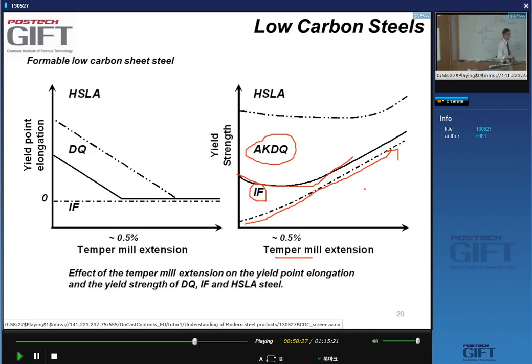So is it necessary to temper roll IF steels? Well, not to remove a yield point. But remember that in temper rolling you achieve three things: removing the yield point elongation, applying a specific roughness, and final correction to the strip flatness. So two of these are still required for the IF steel. You don't need to remove a yield point elongation, but you do need to apply a specific surface roughness, for tribological reasons and for visual appearance after painting. Both are important. And improving the flatness of the sheet is also an important point.